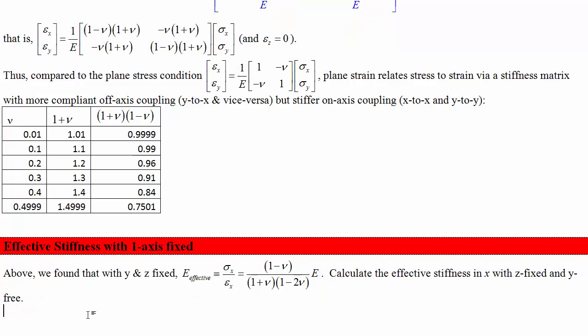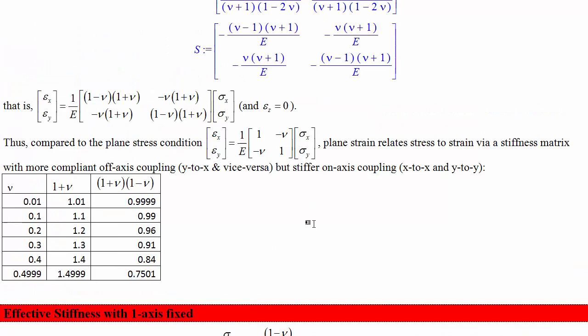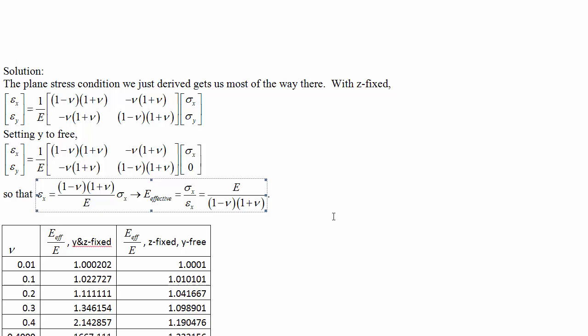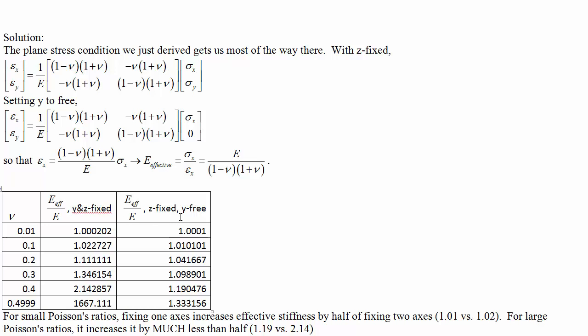Final example: with Y and Z both fixed, the effective Young's modulus in X is larger by the full factor. Now using the plane strain result with sigma Y = 0 and Z fixed but Y free, we can find the effective stiffness as Young's modulus divided by a different factor. Comparing these two cases, in the small nu limit the material is about twice as stiff with both axes fixed versus just Z fixed, but as nu increases, having both axes fixed makes a much bigger difference.